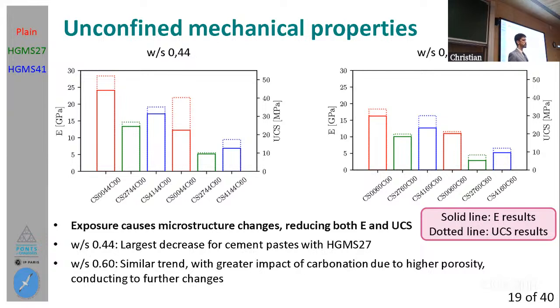Then what we can also see is that after carbonation, from here to here, we have a decrease in all the parameters, in those unconfined parameters. And this happens for all the cement paste. This happens also here, from here to there, from here to there, and from here to there. And what we have is that the larger decrease occurs for the cement paste with a weaker sphere, the green one, the HGMS27.